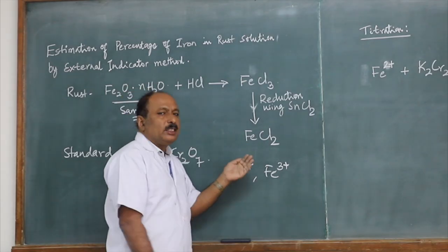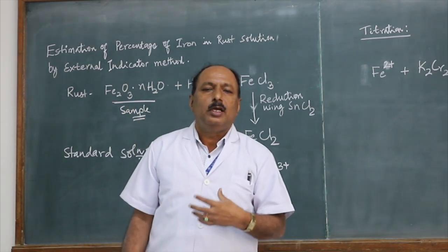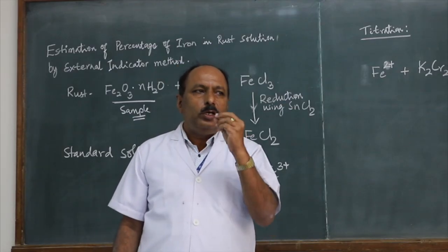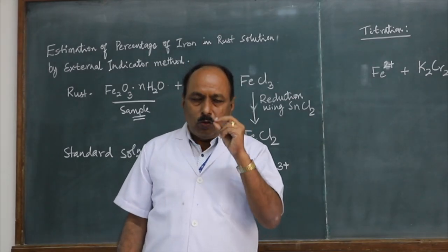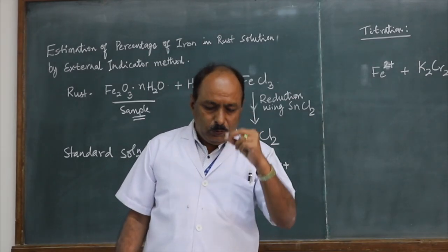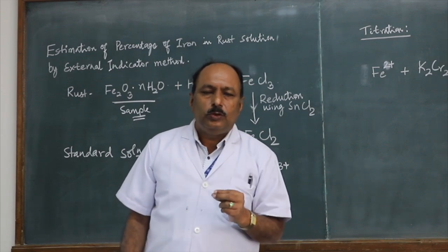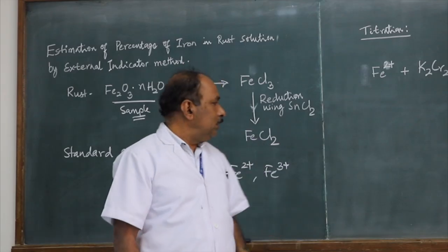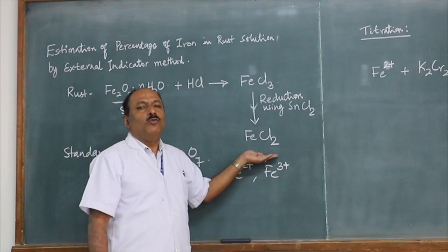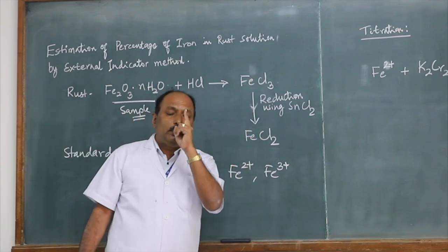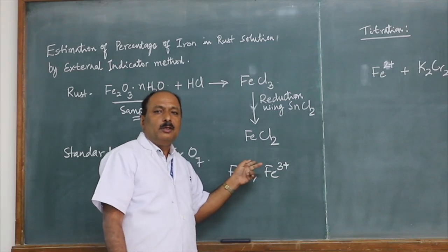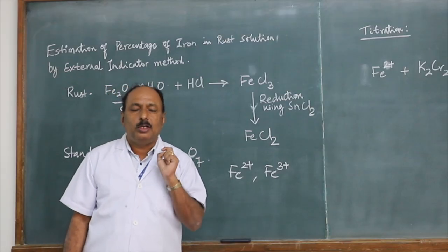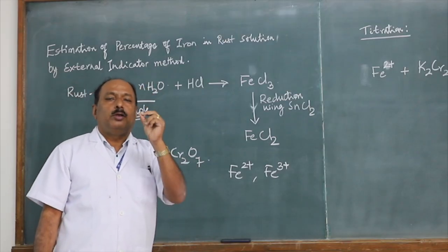Then, to remove this excess stannous chloride, the conical flask is cooled to room temperature under running water, and then 1 test tube of cold water is added. To that solution, 1/4 test tube of saturated mercuric chloride solution is added at once, so that the solution becomes silky white. This reaction should take place in that direction only, to get a silky white precipitate. Contrary to that, if you get a black precipitate instead, it is wrong. One needs to redo the experiment completely.